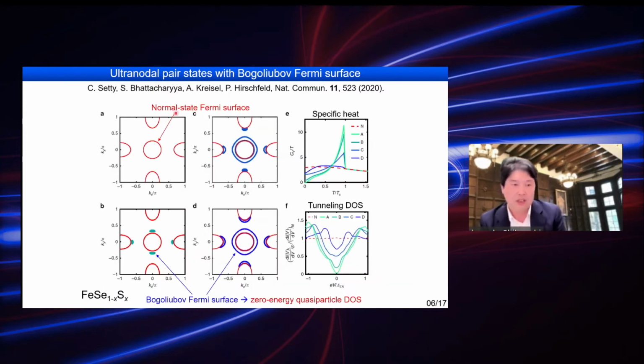So if you look at the electronic structure, in the normal state of iron selenium, you should have this kind of multi-band electronic structure. You have a hole band in the center and the electron band in the zone corner. But in the superconducting state, you may find some parameter range where you can actually have the Bogoliubov Fermi surface, shown by blue lines.